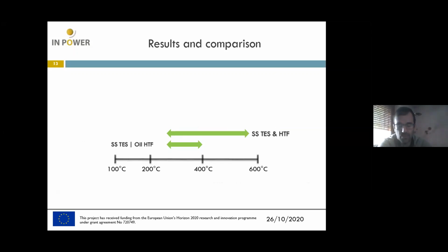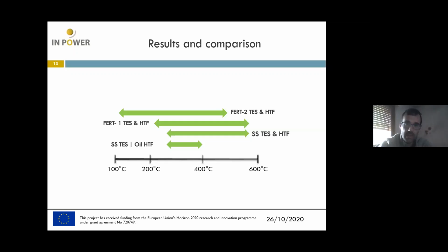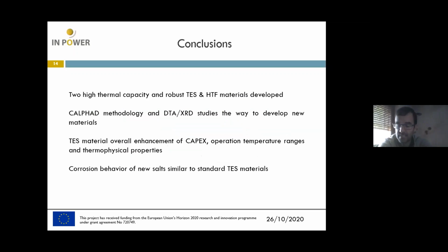So finally, to compare in a graphical way, you can see the temperature range in an indirect system with solar salt and oil. Then in a direct system with solar salt and with this salt as also a direct system, we can increase the gap a bit. And in the case of the other salt, we can see that we can reach very low temperatures while only decreasing the high temperature about 100 degrees. So for certain applications, this salt can be studied and can be considered to be installed. And okay, this is all.